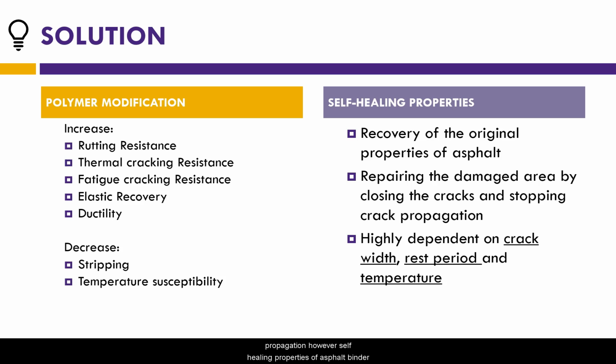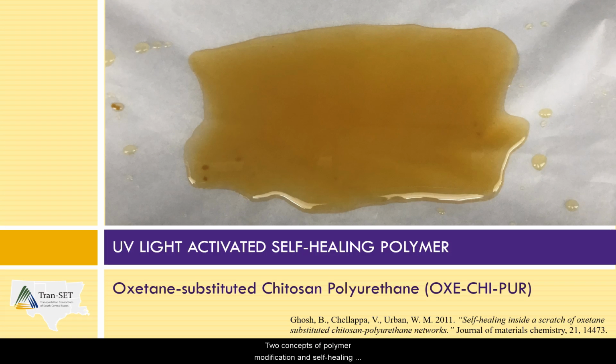However, self-healing properties of asphalt binder are highly dependent on crack width, rest period, and temperature. Using two concepts of polymer modification and self-healing abilities of asphalt binder, an innovative self-healing polymer was used in asphalt pavement to enhance its performance while increasing its service life. The self-healing polymer used in this study is called oxetane-substituted chitosan polyurethane and was introduced by Ghosh.